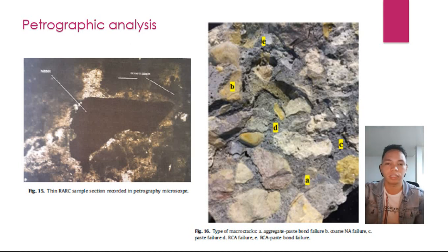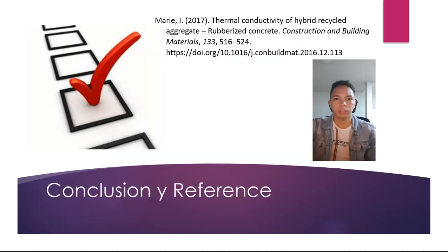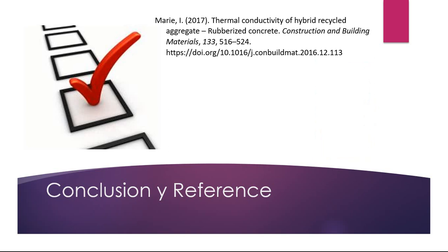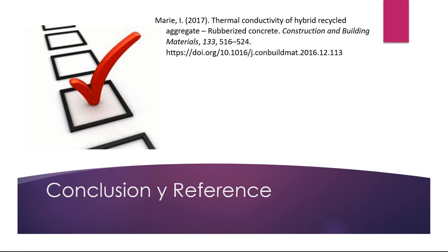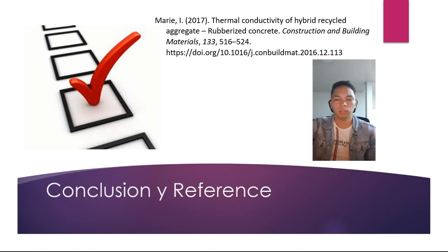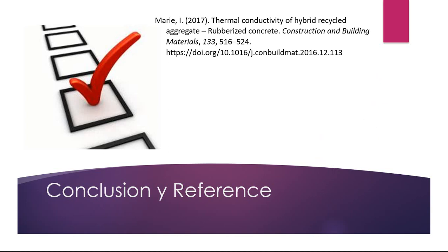Conclusion: it is found that while RCA generally reduces compression resistance of concrete due to increased aggregate water absorption and weak residual mortar layer, it is possible to produce RRC with improved thermal insulation property due to its lower thermal conductivity compared to conventional concrete.